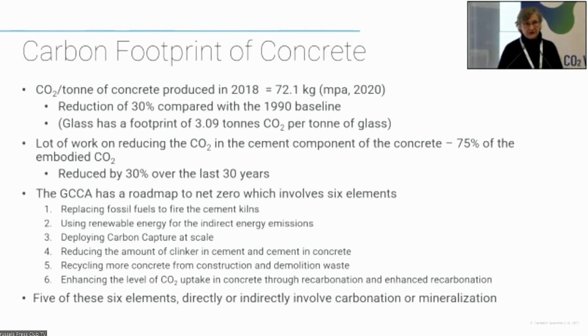Replacing the fossil fuels in the kilns. So instead of burning coal and gas, move to alternative fuels, including refuse-derived fuel and indeed hydrogen. There's one plant in the UK that has trialed the use of hydrogen to fire their kiln, unfortunately in conjunction with other fuels. Changing to renewable energy for the other energy requirements of the plant. Deploying carbon capture at scale, well, they're going to have a problem because what are they going to do with the CO2? Because the cement works tend to be dispersed sites. Reducing the amount of clinker in the cement.